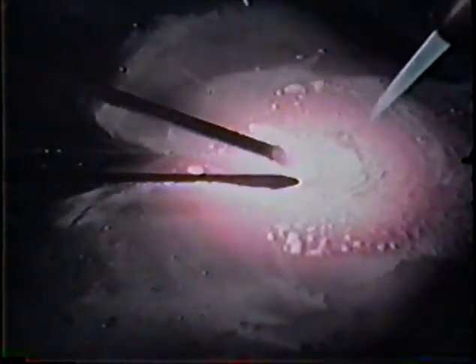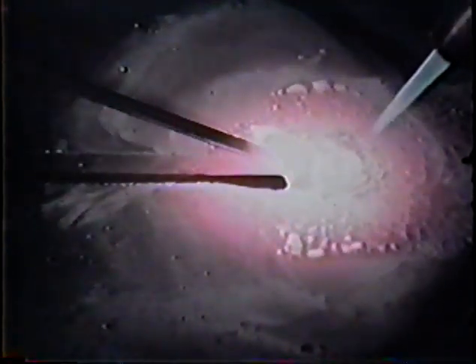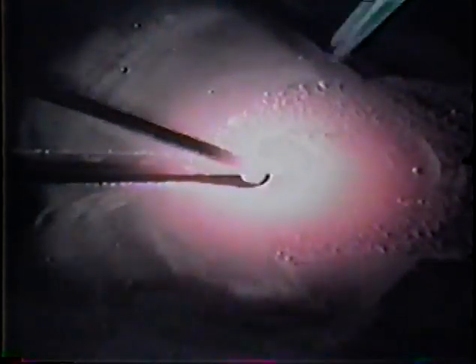If the puddle appears to be too cold and the edges are not melting and fusing, then increase the angle of your torch slightly toward the perpendicular to increase the amount of flame contact. This adds more heat to the puddle.